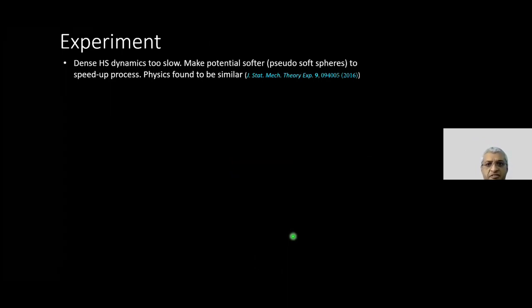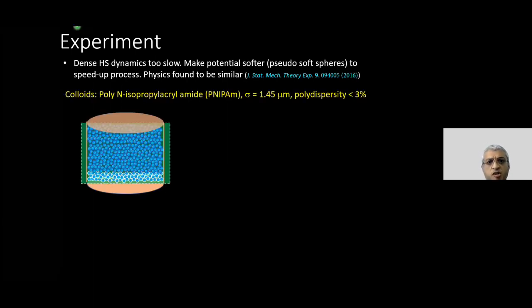Now, the experiment itself: hard spheres, because of the very steep repulsive interaction, mean that rearrangements are very, very difficult to make. So what I'm going to do is take my colloidal system and make the potential a little softer so that I can speed up rearrangements in the system. All right. And I am also guided by a study which said that if I were to do that, the physics should not change all that much. Okay. So I'm going to work with soft spheres, and the soft spheres that we work with are called PNIPAM particles. That's some details of the particle. They have a very small polydispersity, so they have a high propensity to crystallize.